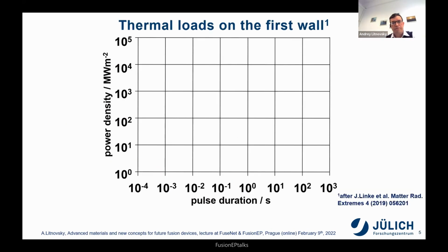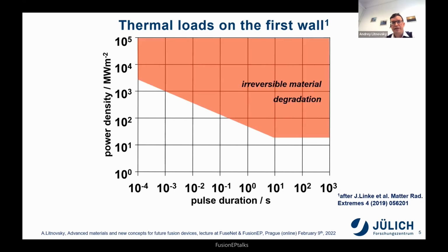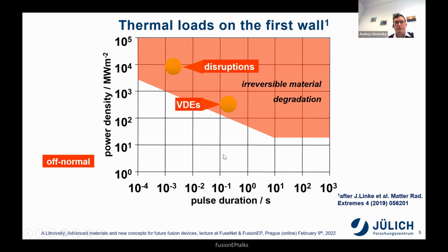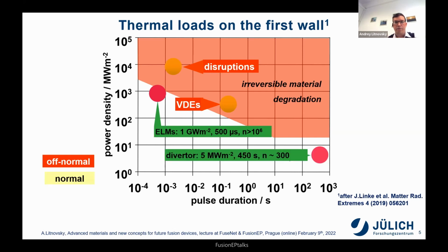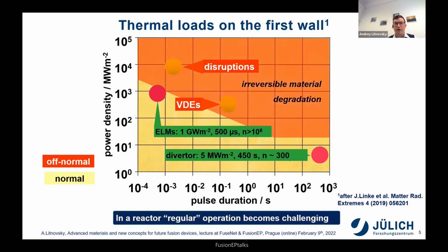And if we look at the conditions which are awaiting our materials in the fusion plasma, we can see this area of irreversible material degradation. This is where we really lose the material, of course, and this is the power density, and this is the duration of the pulse. So we can tolerate disruptions and vertical displacement events for a very short time only. But even if we look at the long pulse duration, and we remember that we will have a pulse of 2 hours in the power plant, we can see already that the tolerable loads, the power densities, become really quite small, which the material can take. So the time plays against the material lifetime. That means that in the fusion power plant, in the reactor, already regular operation becomes challenging.